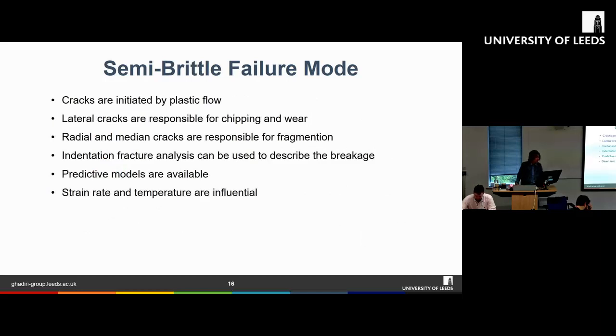So, a quick summary for the semi-brittle failure mode. Cracks are initiated by plastic flow, and lateral cracks are responsible for chipping and wear. Radial and median cracks are responsible for fragmentation. Indentation fracture analysis can be used to describe the breakage, and there are a lot of predictive models available in the literature which we can use to describe this type of failure. And for semi-brittle failure, strain rate and temperature are influential.